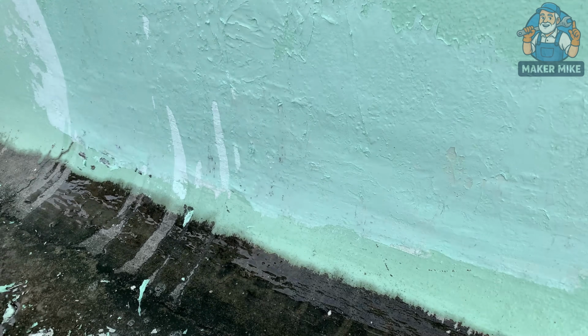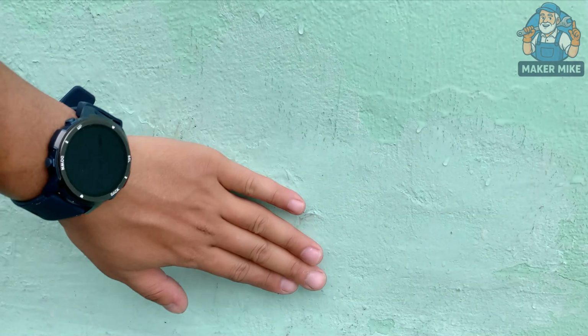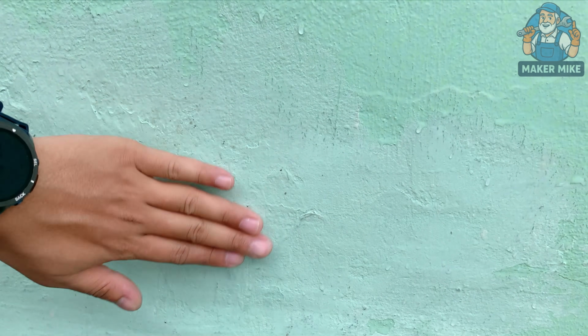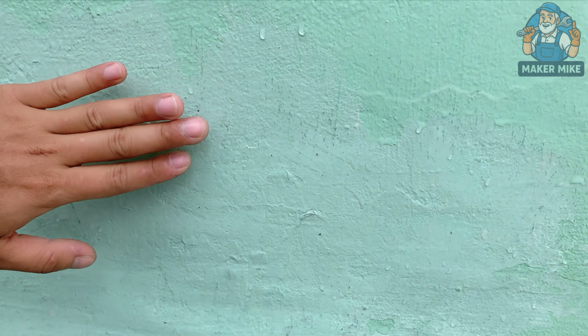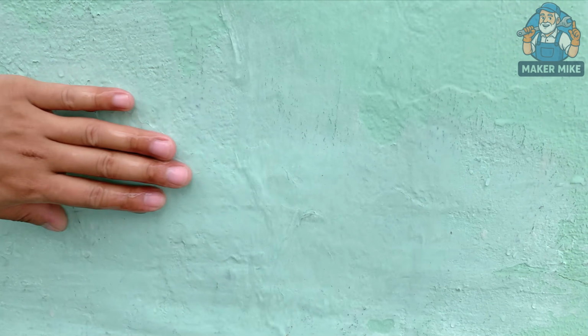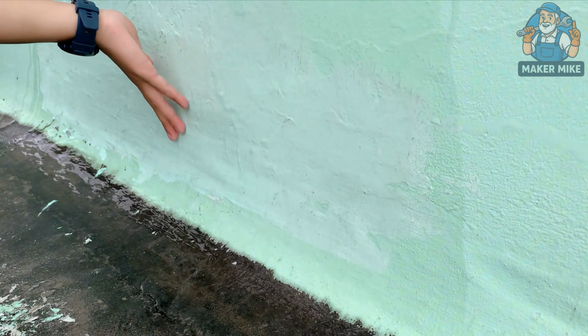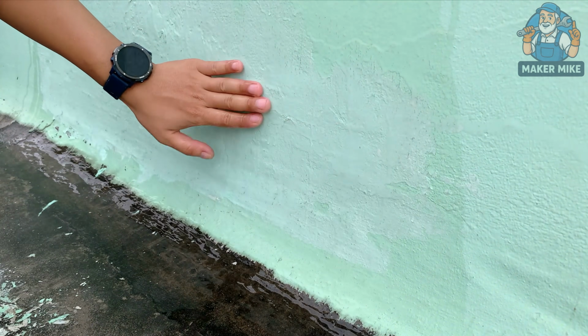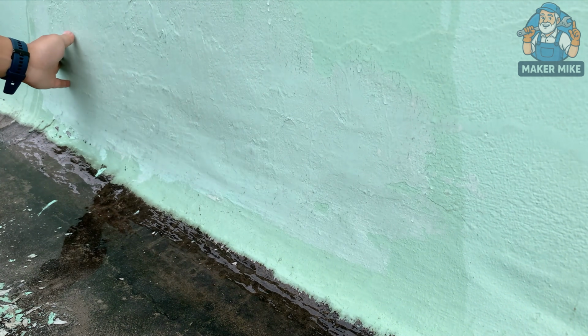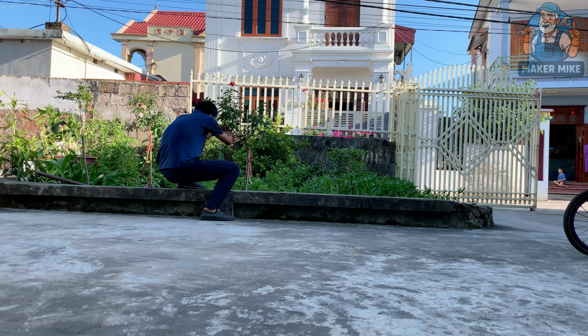Back at the wall, repeat the same test once the patch dries. Pour a small amount of water across the repaired area. The water rolls across the surface without soaking into the plaster. The crack is now sealed. The wall remains dry, and the repair blends naturally with the surrounding color.